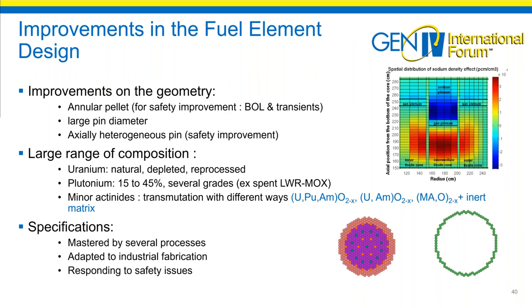During all this experience, we have improved the fuel element design, and the improvements were mainly devoted to the geometry, especially the annular pellet, because of the safety improvement during nominal conditions and also under transients. In order to avoid the fuel melting, we choose the annular pellet. A large pin diameter has also been developed, axially heterogeneous pin also for safety improvement.